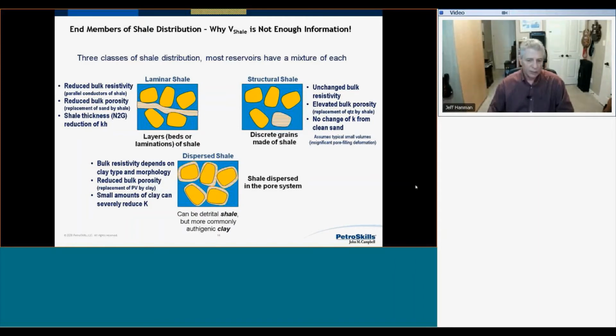There's a little disclaimer here, and this is assuming typical small volumes of these shale grains, because if we have a lot of those, they will deform and they will extrude into the pore space. And if you have a lot, it is detrimental to your permeability. But the typical, what we'll see in scattered rip-ups and those sorts of things, don't really cause much of an issue for permeability. This is the one to discriminate, the dispersed shale class.